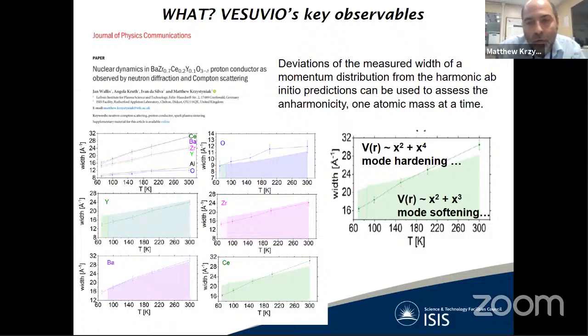If you go into the theory of anharmonicity in the perovskite oxide systems, there is a general result saying that mode hardening above the prediction from harmonic lattice dynamics is a signature of the presence of the quartic anharmonicity, whereas mode softening is a signature of the presence of the cubic anharmonic term in the local potential. So by simply contrasting the measured and lattice dynamics predicted values of zero point energy, we can characterize the interplay between different types of anharmonicity as the temperature changes and phase changes occur in the system.